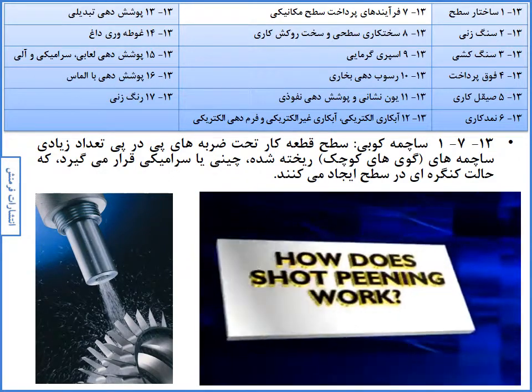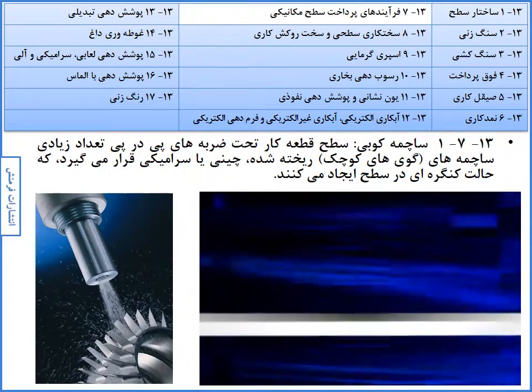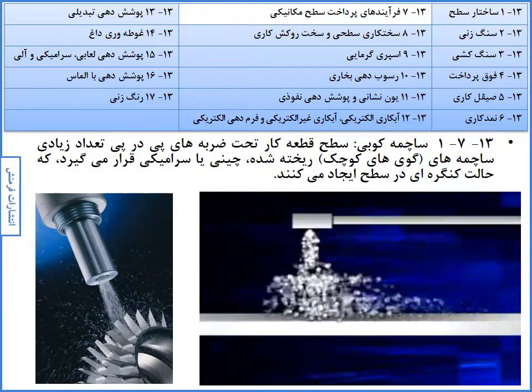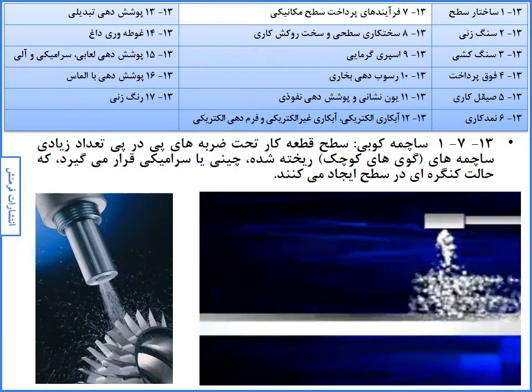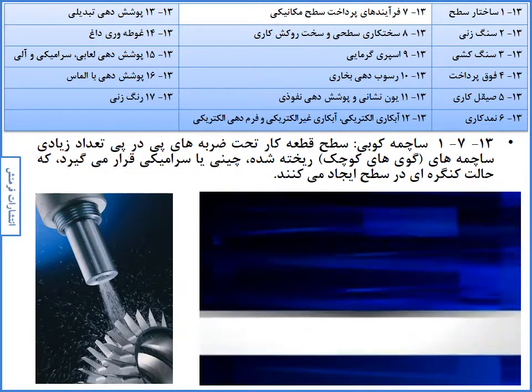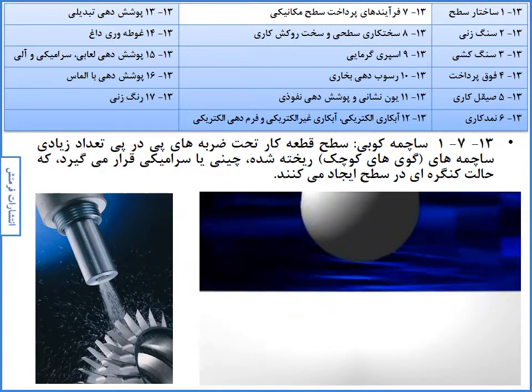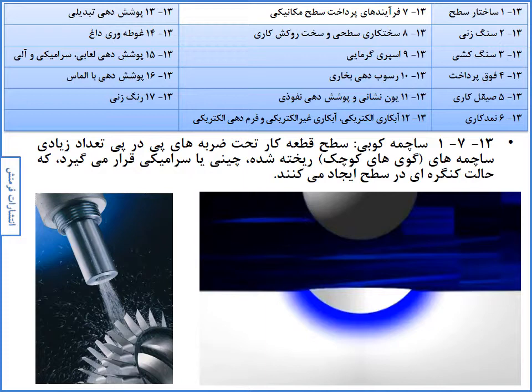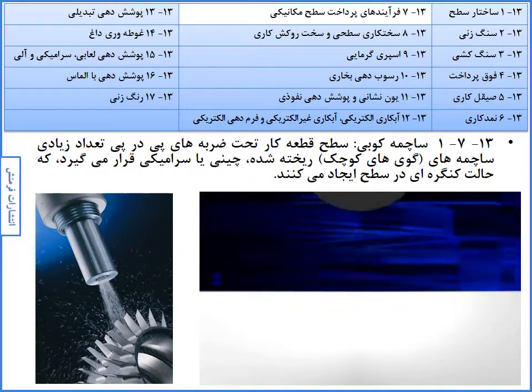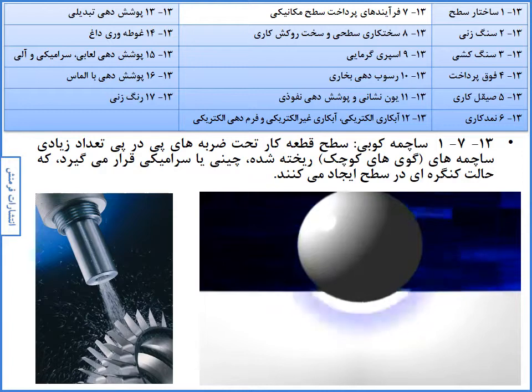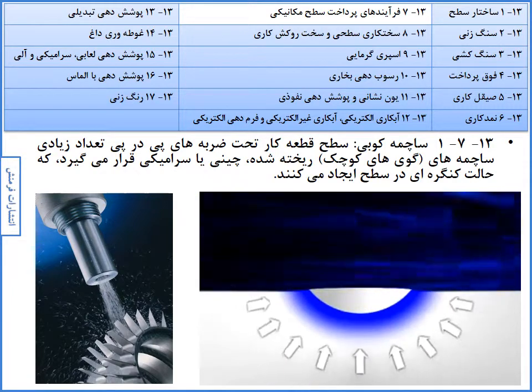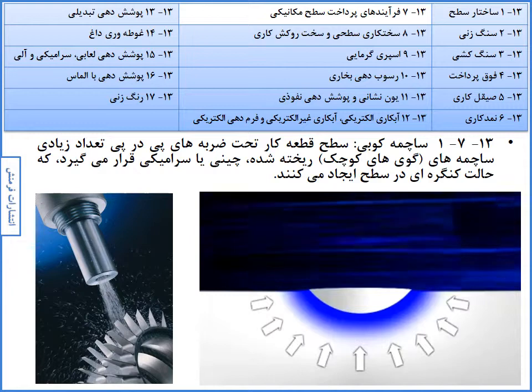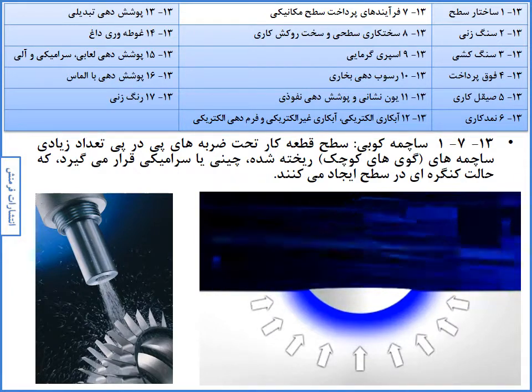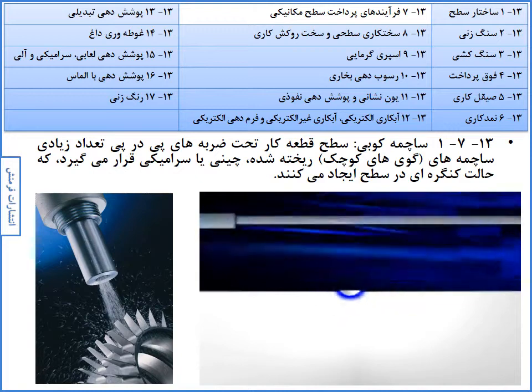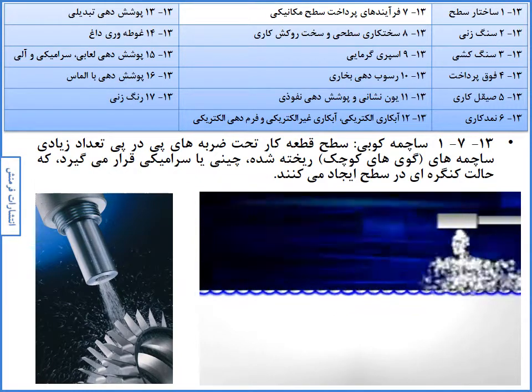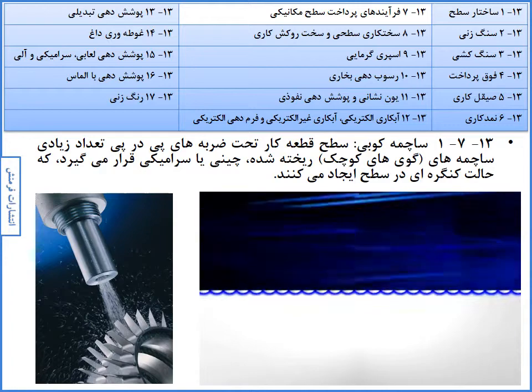So, how does shot peening work? Simply put, it is a controlled process of making dents. The surface of a part is bombarded with small, spherical media called shot. Each piece of shot acts as a tiny peening hammer that creates a dent in the metal surface. In order for the dent to be created, the surrounding surface layers must yield and stretch. The non-yielded layers beneath the dent resist the stretching deformation and thereby create a residual compressive stress zone around the dent. Overlapping dents from multiple shot impacts develop a uniform layer of compressive stress.